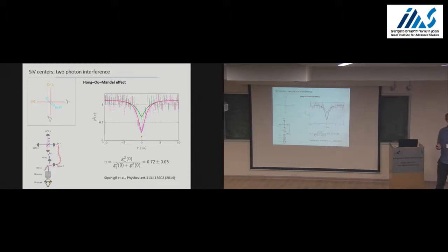So there are two different mechanisms. One is related to static line shift between different color centers, and that's related to strain in the material. And the phonon sideband occurs because when exciting the atom from ground to the excited state, you not only excite the electron, but the electron wave function basically changes and it gets kicked to the carbon nearby.